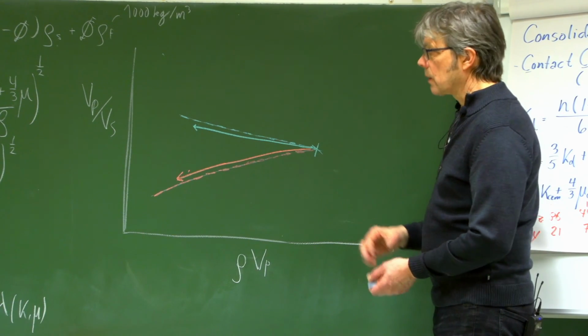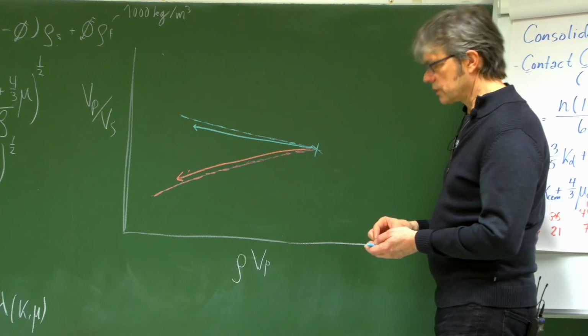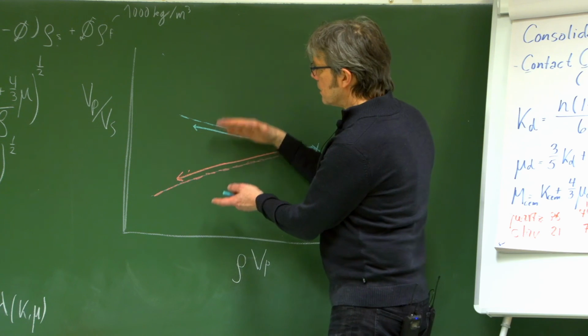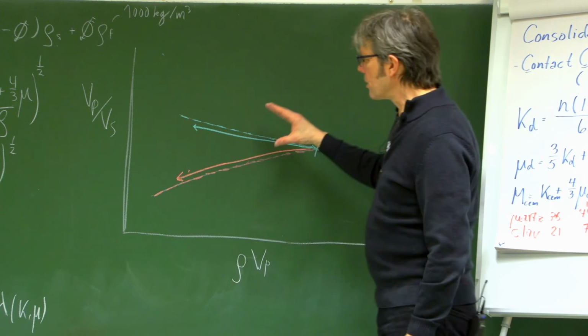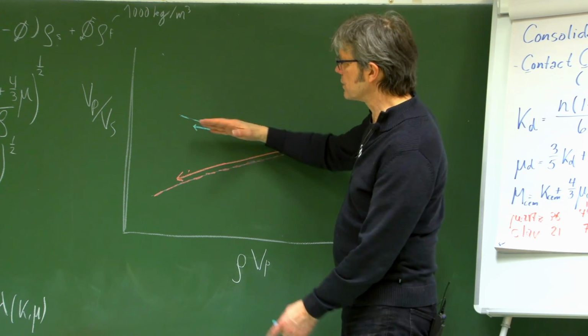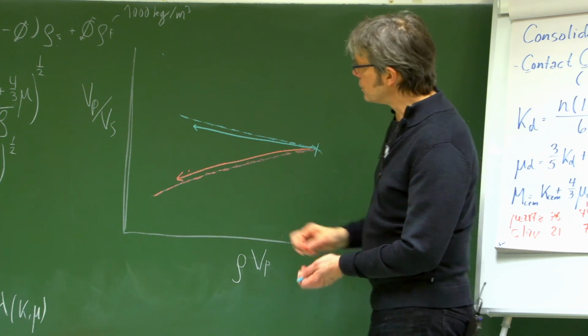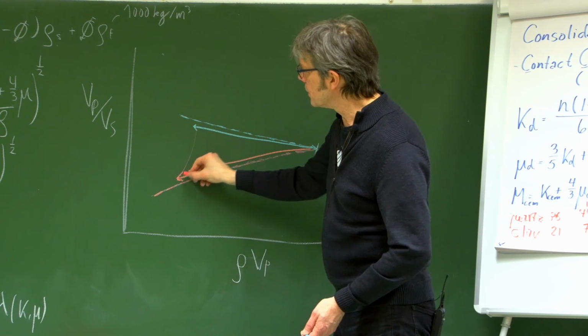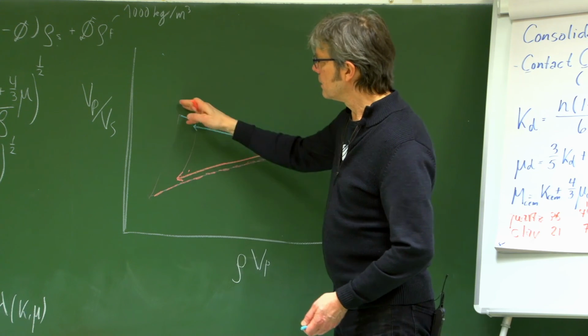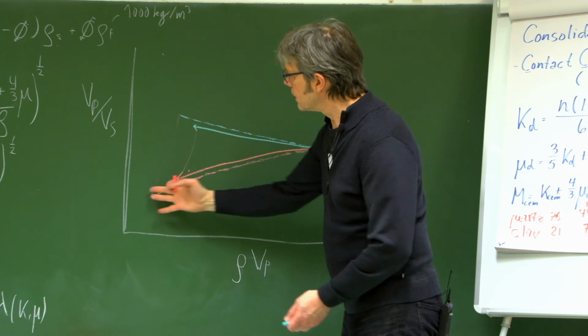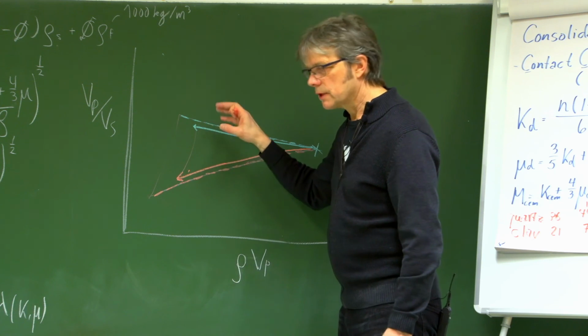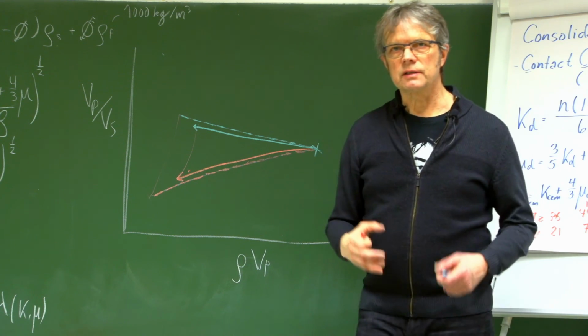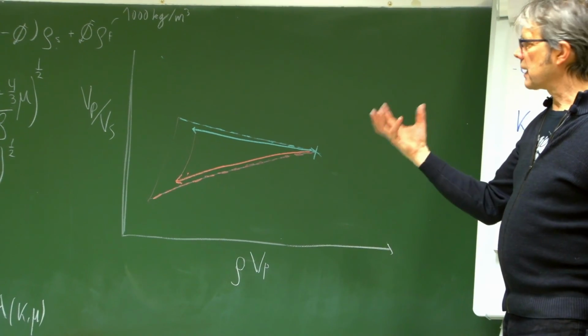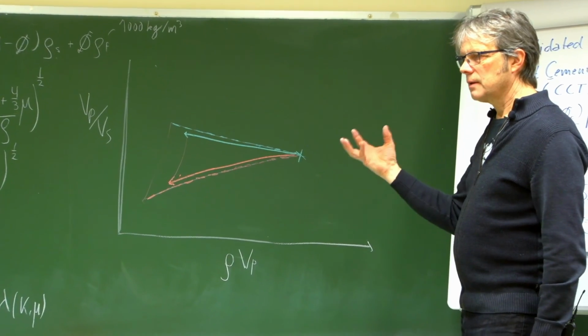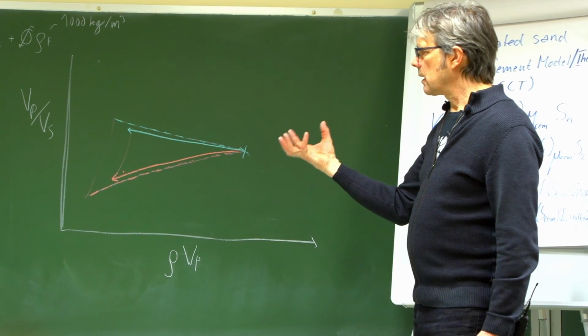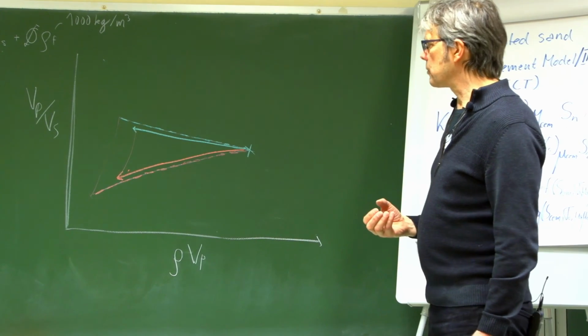So the effect of adding cement into the system is losing the gap. The smile becomes less. The mouth is closing. And of course also the fluid effect is reduced compared to this one. You see that the change in the VP over VS and also the acoustic impedance becomes less when cementation is present. And of course, that's the container. As the sand becomes stiffer, the container is less compressible and it's more difficult to feel what's inside.